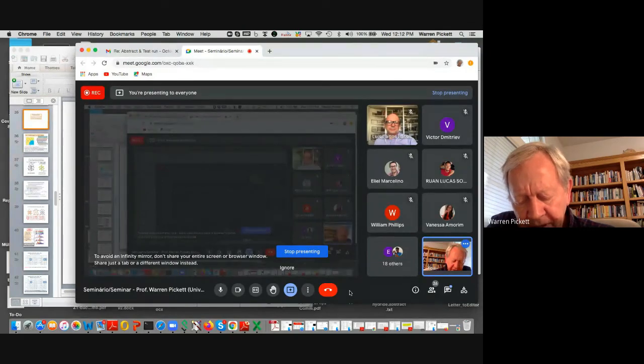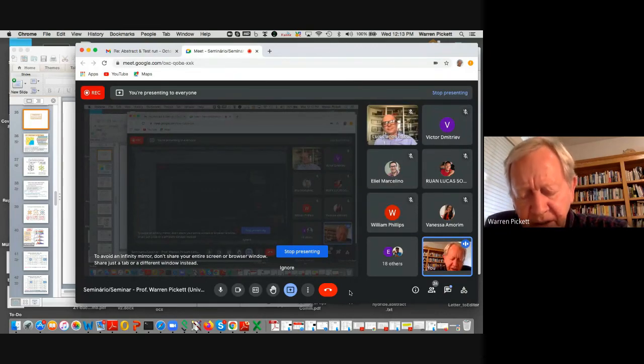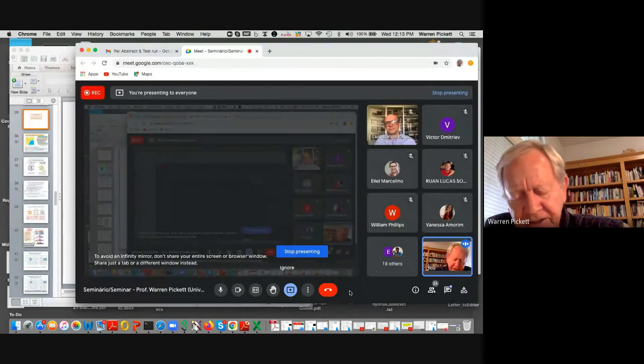Groups are now doing susceptibility studies, and susceptibility swings at TC are quite large, relatively speaking. Of course, they have very tiny samples. And what's inside the diamond anvil cell when it's pressed like this? There's no guarantee that it's very homogeneous. What is done typically is to press and then release a little bit and apply some heat, that is laser heating, to try to anneal it a little bit, press and release and so forth. And so the sample quality is a real question, homogeneity, and the lack of very many probes that you have.